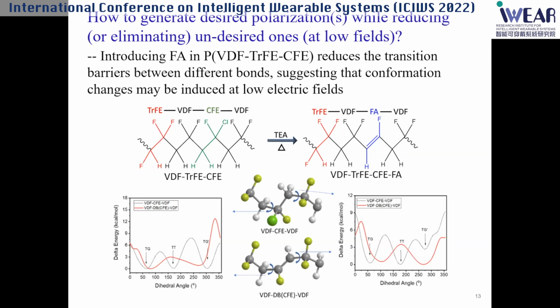This is an interesting question, but it will take a while for us to find an answer. Last year we found that by converting a small amount of CFE monomer into this double bond, we call it FA bond, we could reduce the barrier for the conformation - for example this is the trans-gauche, trans-gauche prime for this polymer monomer unit. This is the CFE, and this black curve is another side. You see the barrier is relatively high. Now if you convert the CFE into the double bond called FA, you can see this red curve - basically the barrier for this dipole bond to rotate is much smaller.